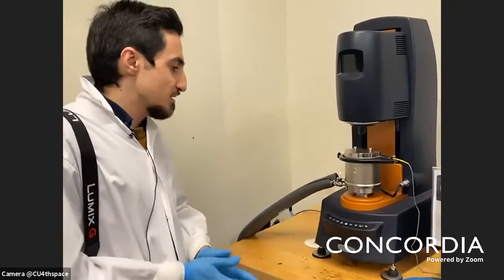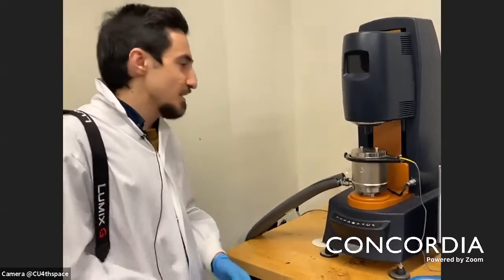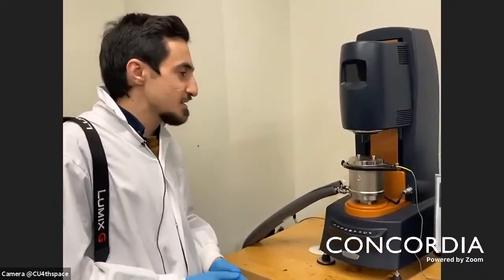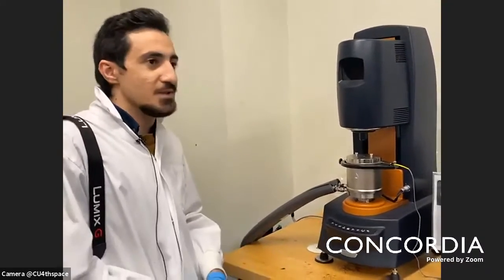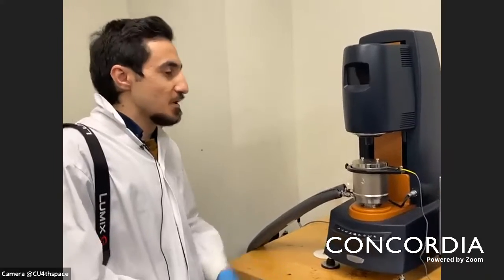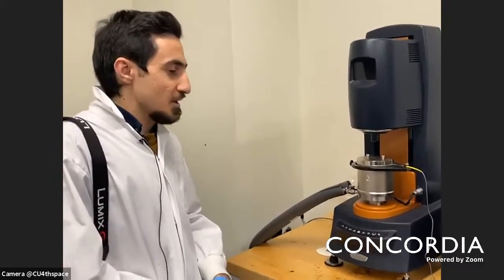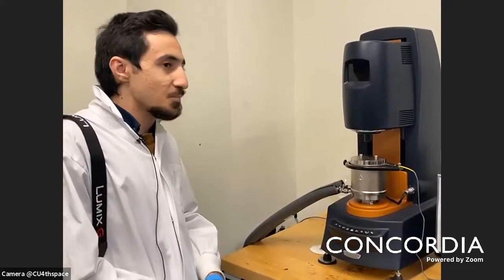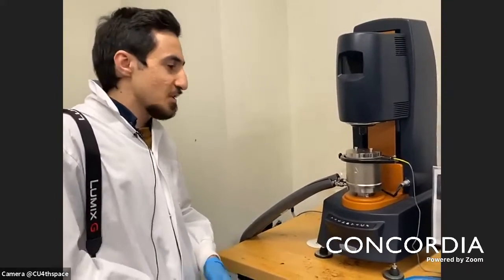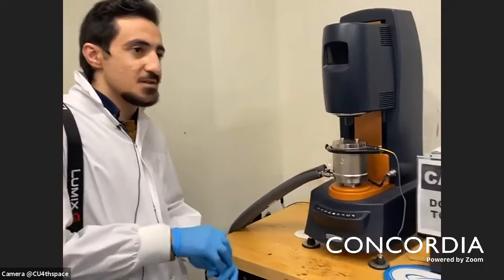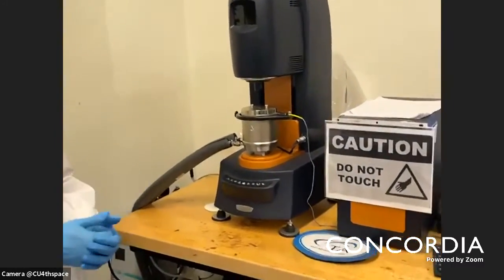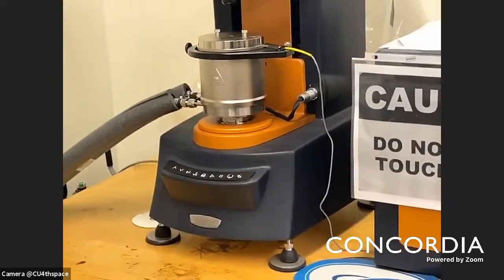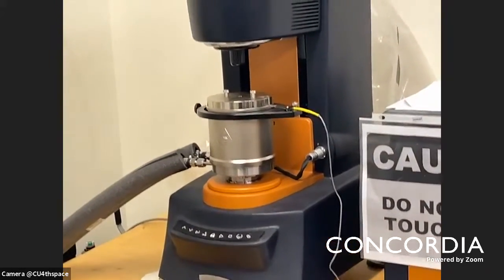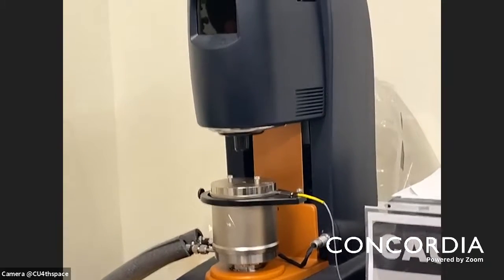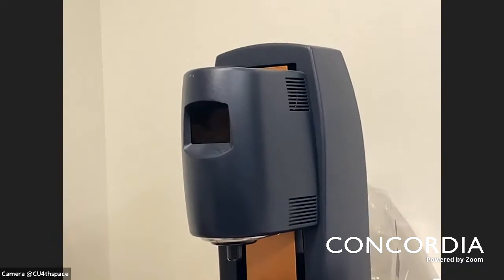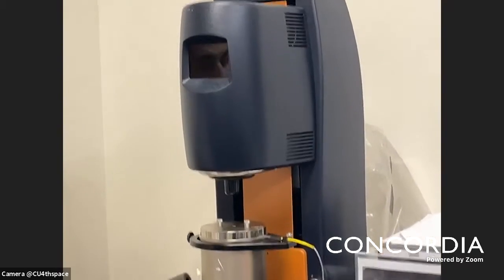As I said, this kind of material is heat sensitive, and at various temperatures you can see different responses. And it's very important because, for example, if you are making a coil, by increasing the current, the temperature of the coil will increase. And because this coil will be installed on this MRE, the response of the MRE will be different because of that coil. Here we can measure this response with this device before making the structure.